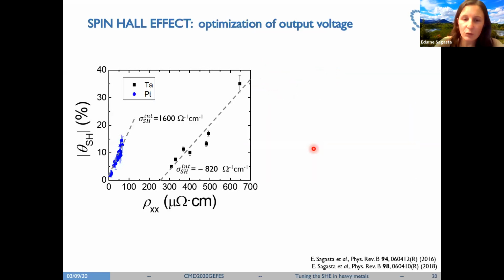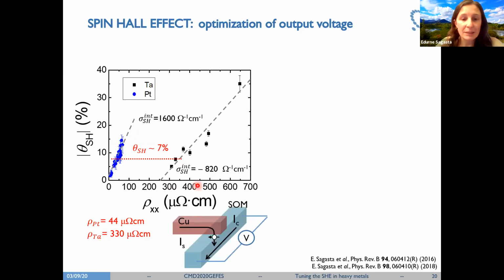So this question we will answer in the very last part, and I will start from the very same plot because we can extract very interesting information, much more information from here. So now we will take just one platinum device and one tantalum device where they are characterized with the same spin Hall angle. So we see clearly that the corresponding resistivity is much larger for the tantalum. So this means that if the spin Hall angle is the same, the charge current that will be generated will be the same, but the voltage drop that we are expecting for tantalum will be almost 1 order of magnitude larger because of the higher resistivity.